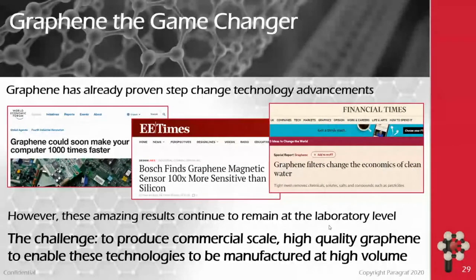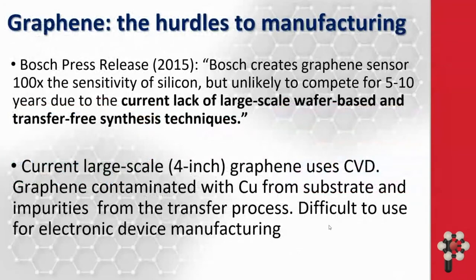Bosch finds graphene magnetic sensor 100 times more sensitive than silicon. They assembled it by hand from tiny flakes, it wasn't manufactured. And then graphene filters changed the economics of clean water. So these things were all predicted, and they haven't happened. And Bosch actually issued a press release in 2015, and they said, we've created this sensor 100 times better than silicon, but unlikely to compete for 5 to 10 years because of the current lack of large-scale wafer-based and transfer-free synthesis techniques.